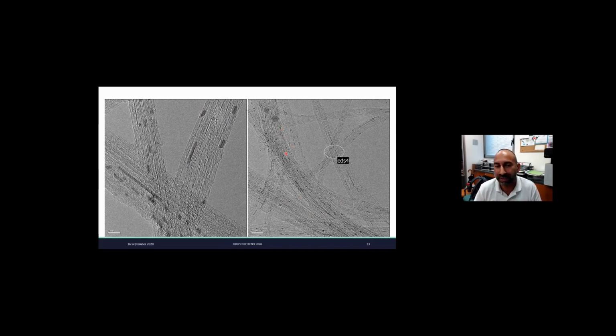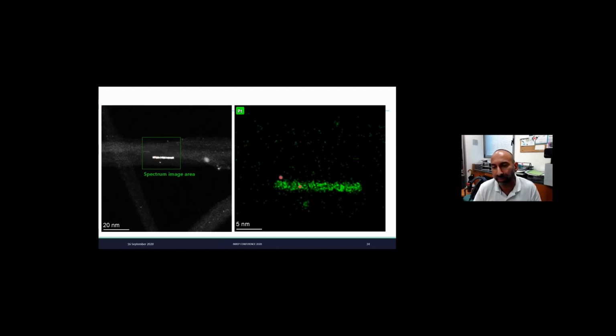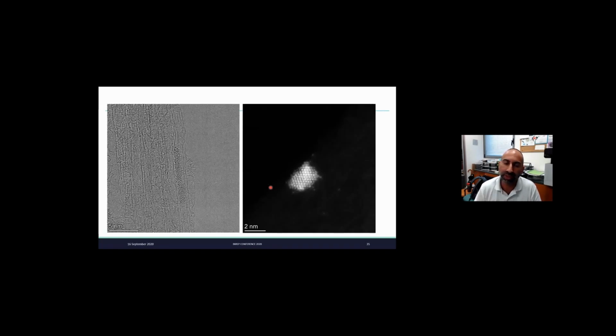And we know that this is inside because we have here some image of EDX and we see the platinum inside the nanotube. We see that this is crystalline and the crystal is really following the walls of the nanotubes. Sometimes we have some defects. So these are the platinum atoms that we have in the nanotube.